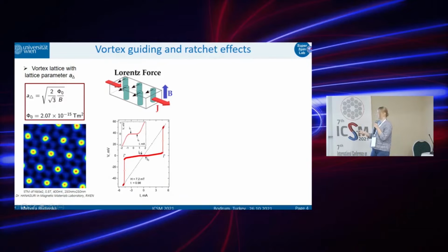So where we have the plateau, it means that they are all pinned. Once they start moving, there will be dissipation of energy, voltage is rising, and it all comes to a point, the flux flow instability, where it comes to a very quick abrupt jump from the superconducting to the normal conducting state. And in our structures, we would like to influence the dynamics.